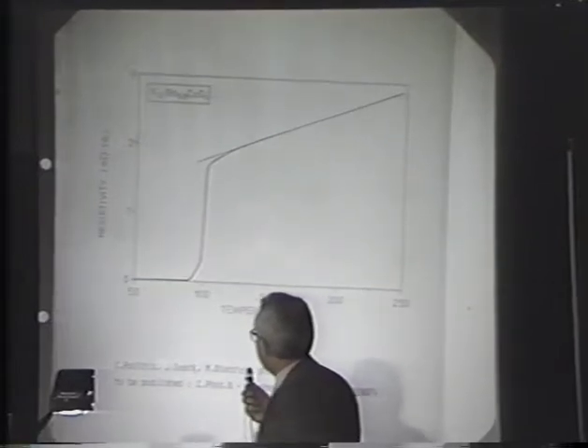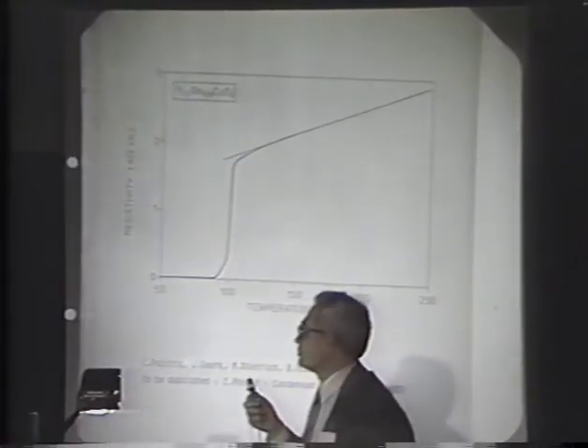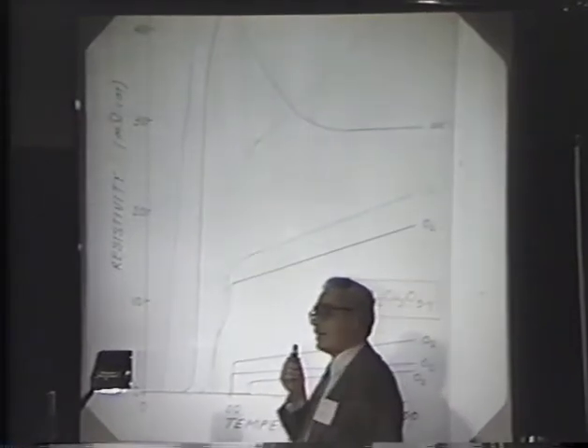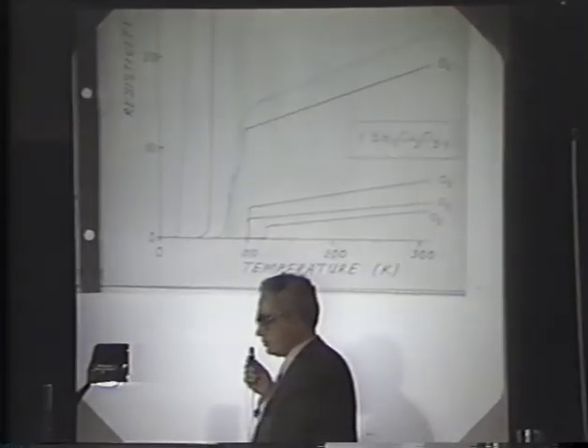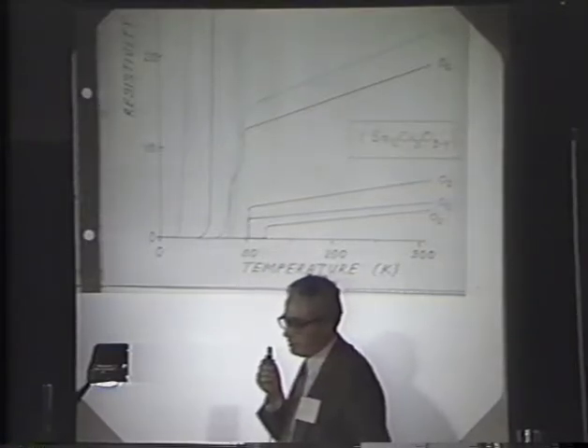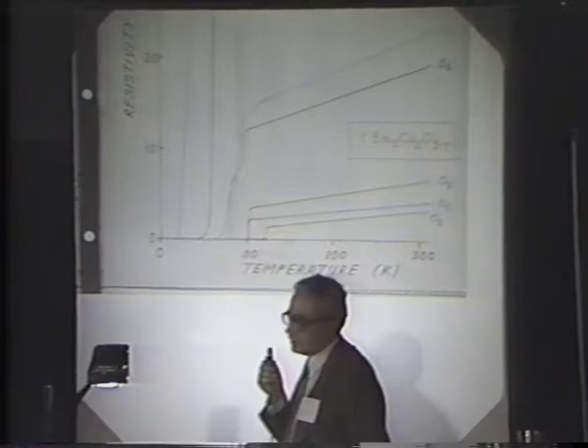The transition onset is 125. Even the 10 to 90 transition is 110. You had another view graph with several oxygen pressures. That's not the same curve that you showed that was at 120. Let me show. The oxygen pressure is an over pressure of 2.5 bar of oxygen, and the sharp transition is 125, 124.